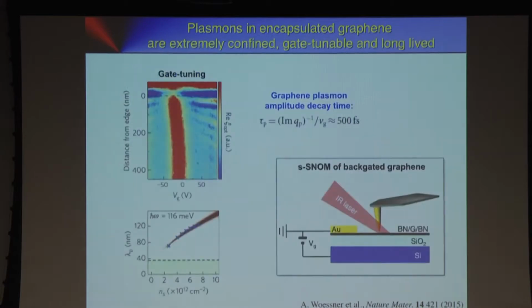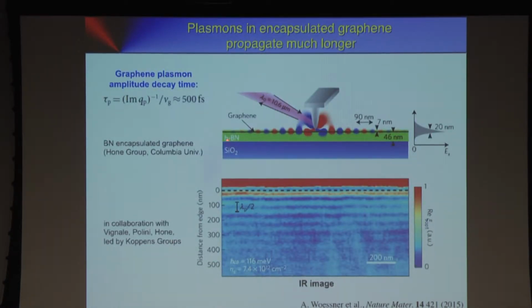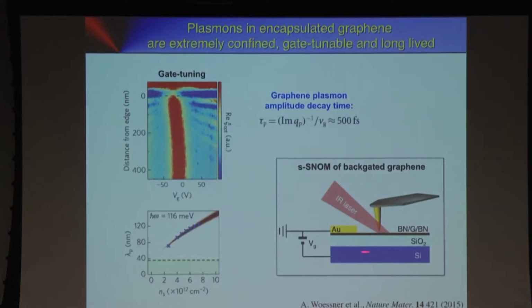Then I just want to give you another example. I mentioned already, the Fermi energy determines the wavelengths. And so we did the following experiment. We took this sandwich here. And here we have the graphene, boron nitride, silicon oxide, and below is silicon. And we can use this silicon as a backgate. And that's schematically shown here. Here's the boron nitride graphene sandwich. Then we have a gold contact, and we use the silicon as a backgate.